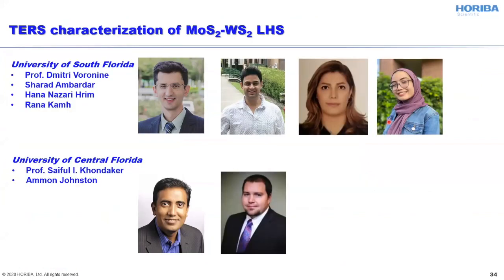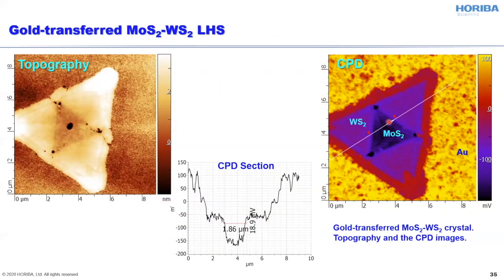Okay, so of course we are running multiple collaborative projects with our prospective and existing customers. And we were lucky to have a sample, actually a control sample, for a different project that we were doing with guys from Florida, the group of Dmitry Voronin and Saiful I. Khondaker. The control sample was also a molybdenum disulfide, tungsten disulfide heterostructure grown pretty much in a similar way. And when we transferred this crystal to gold and ran first AFM characterization, we observed a very similar picture to what we observed in the samples prepared in Alabama.